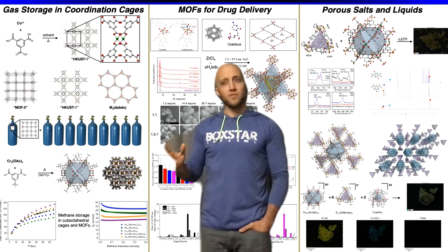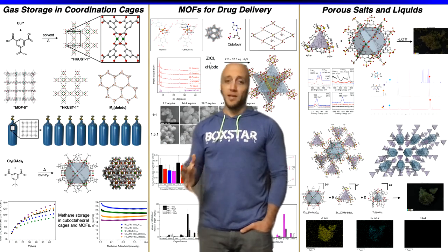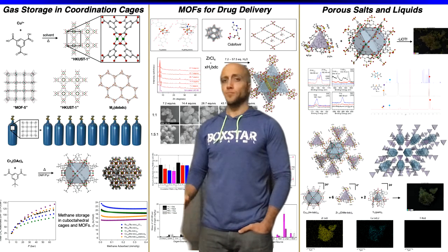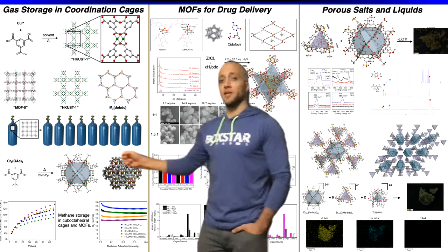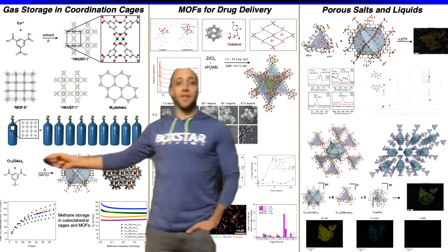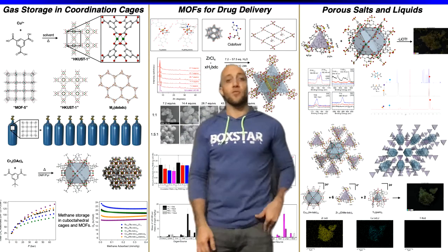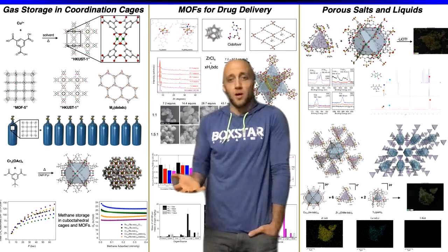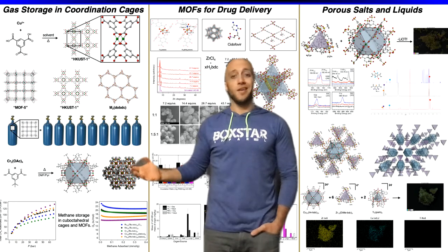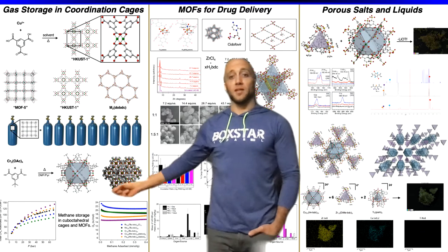So my group is somewhat focused on MOF synthesis and characterization for gas storage, but we're really excited about porous molecular materials to do this job. So kind of like this MOF synthesis, we can take an organic linker, react this with a metal salt, and these assemble in solution into now these molecular clusters. So instead of three-dimensional solids, they're just porous molecules. So here's an example we published recently. This chromium cage has a high surface area, it's very stable, and it absorbs a lot of methane.